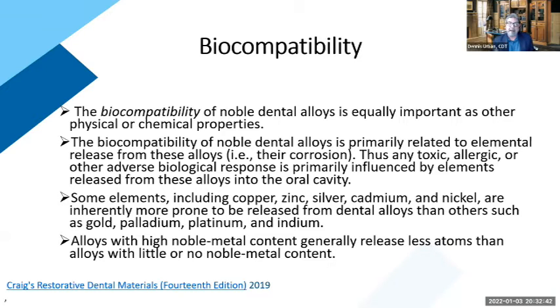Yep, the biocompatibility of noble alloys is equally important as other physical or chemical properties. The biocompatibility of noble alloys is primarily related to elemental release from these alloys, or their corrosion. And this is interesting because any toxic, allergic, or other adverse biological response is primarily influenced by the elements released from these alloys in the oral cavity, and that's from the corrosion. Some elements include copper, zinc, silver, nickel. Nickel is a big factor.